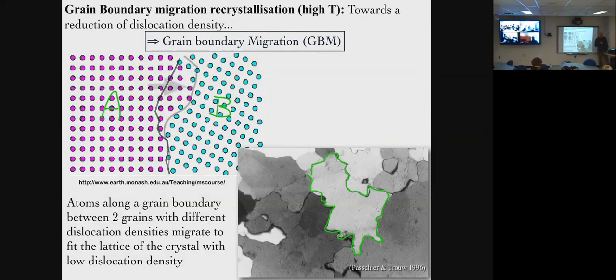And with heat and diffusion, the atoms in crystal lattice B, which is highly distorted, instead of keeping their attachment to crystal B, will break their bond with the crystal lattice that's disorganized and attach themselves to the neighboring, more organized quartz grain. This produces a texture in which the quartz grains with fewer dislocations will grow at the detriment of disorganized grains. Okay? How is that different from bulging?